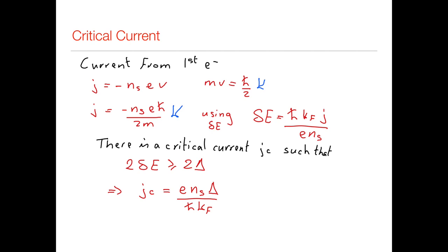That's important because as we know, the gap varies with temperature. So the closer we are to the transition temperature, the smaller the gap is, and hence the smaller the critical current is. So if we want to use a material for carrying large currents, like for example in a superconducting magnet, we don't just want to take our superconductor down to Tc, we'd like to take it well below Tc, because then the critical current it can sustain will be much greater. Okay.